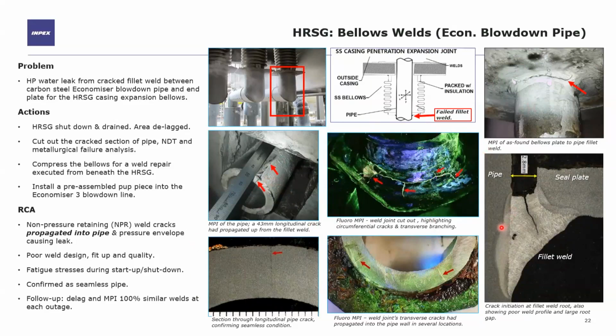A cross-section of part of the fillet weld showed that 1, there was a very large root gap. 2, there's a very poor weld root profile. 3, there's a crack going through it. And 4, that there probably wasn't enough fillet material there for the stresses that this pipe was under, and that's what led to the failure.